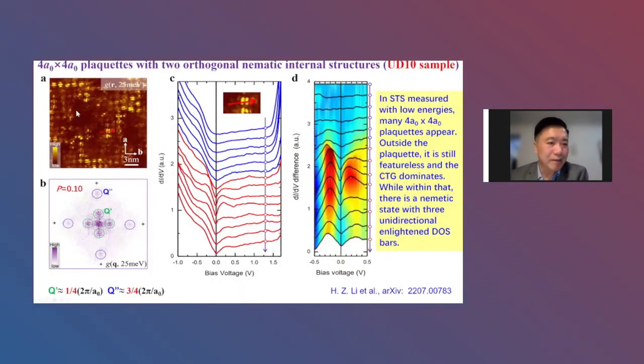And for the 10% doping, we found that actually in the real space density of states mapping, you can see a lot of little blocks with 3 density of states bars inside, okay. We do the Fourier transform, then we see 2 scattering spots. One is 1/4, another one is 3/4. This one means that we have this 4a by 4a block. And this one corresponds to the 3 bars within each block.